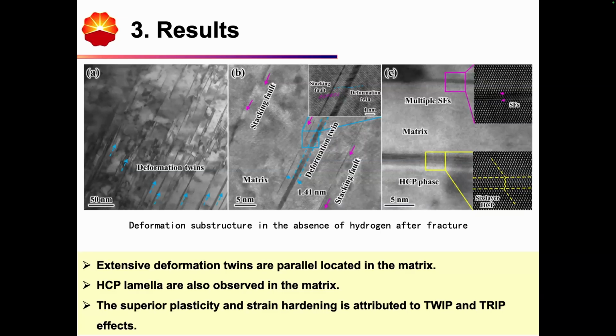Then we applied observations for the fracture in the absence of hydrogen. We can say first that extensive deformation twins are parallel located in the matrix. Besides the deformation twins, we also observed some HCP laminates. Therefore we can conclude that for the materials in the absence of hydrogen, the superior plasticity and strain hardening is attributed to the combined effects of both TRIP and TWIP.